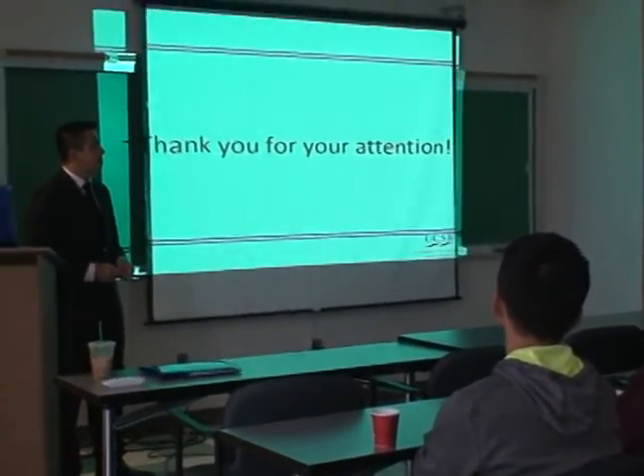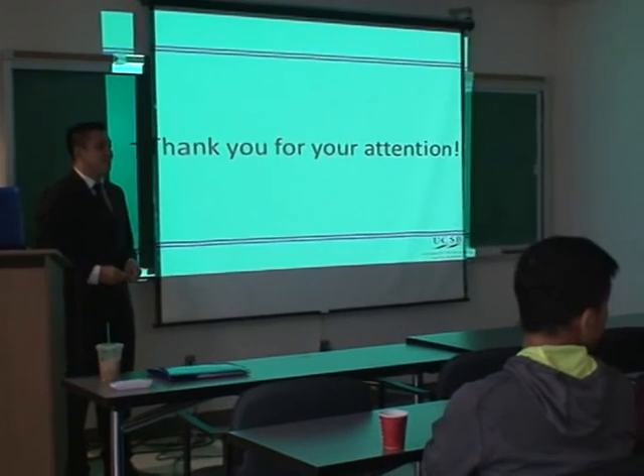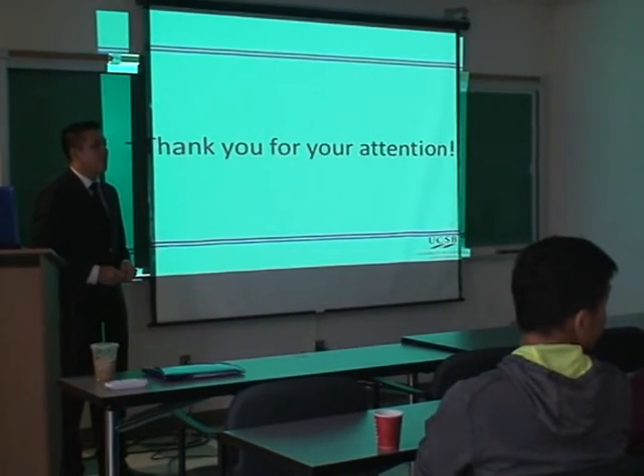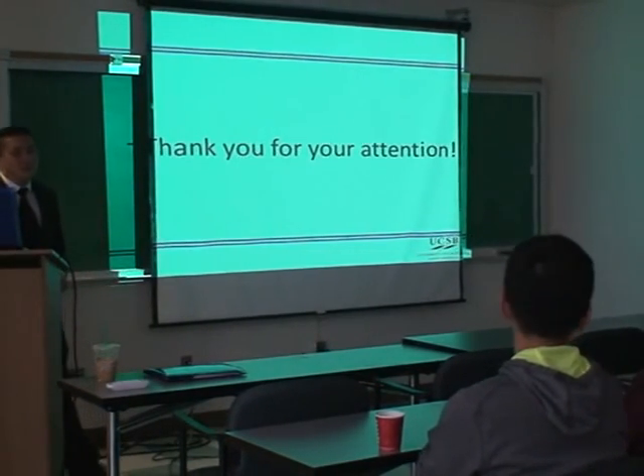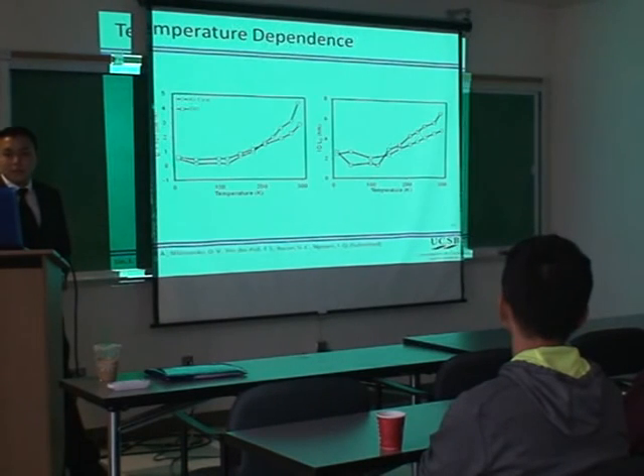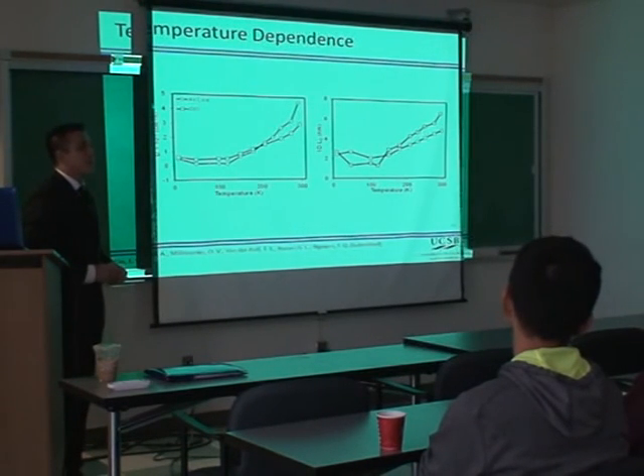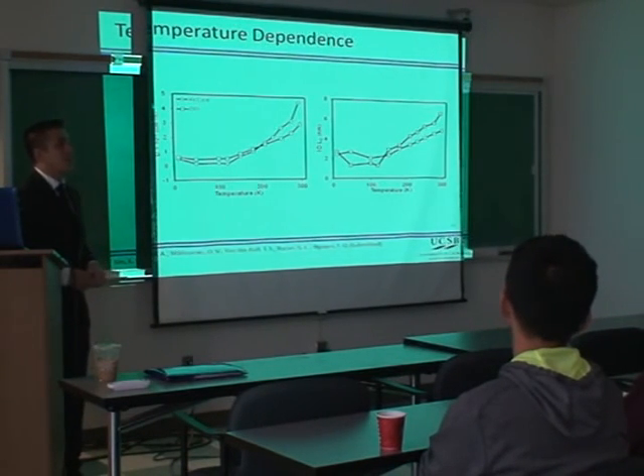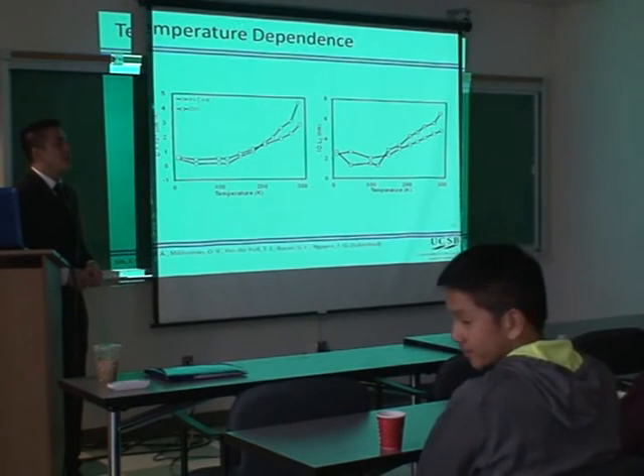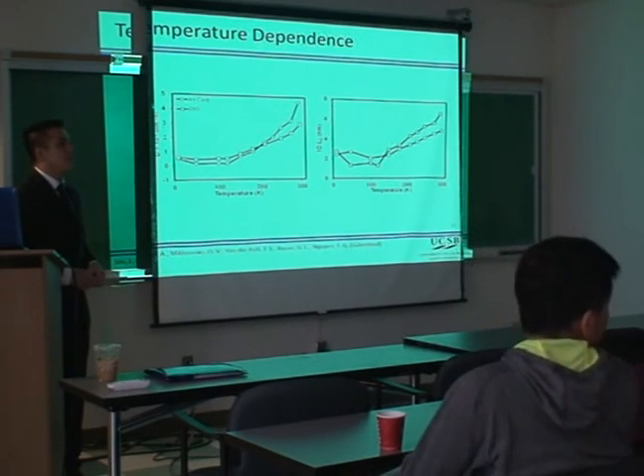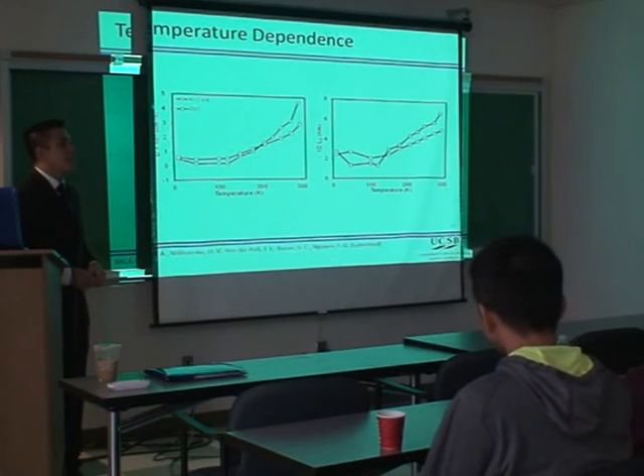Other questions? Alexander? Well, if you look at the temperature-dependent data on the exciton diffusion, you see that there is diffusion at low temperatures when the thermal hopping is frozen, right? So can you think that this is due to Förster energy transfer, because it's dipole-dipole and shouldn't be dependent on the temperature?